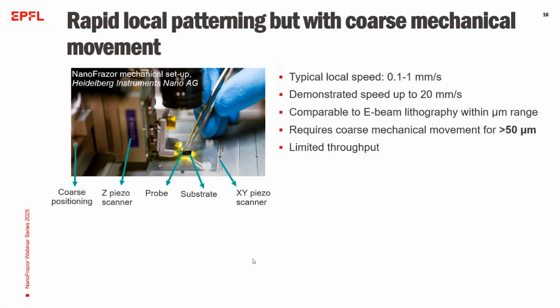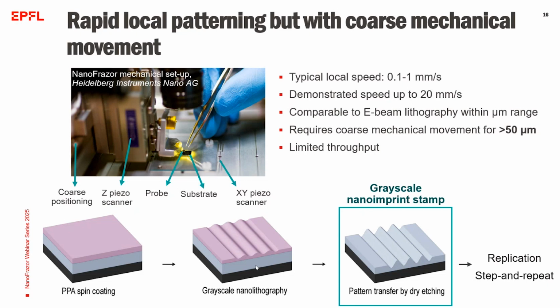As mentioned earlier, the limited throughput of scanning probe-based fabrication is a significant bottleneck for this technique. And despite speeds comparable to electron beam lithography at micrometer scale, it is unfortunately not suitable for now for wafer scale patterning due to the need for coarse mechanical movement outside of the piezo scanner range. To address this challenge, we use grayscale patterned substrates as nano-imprint lithography stamps to enable upscaling through replication, particularly by step and repeat process on large surfaces. Therefore, we can replicate our grayscale surfaces on large wafers many times.